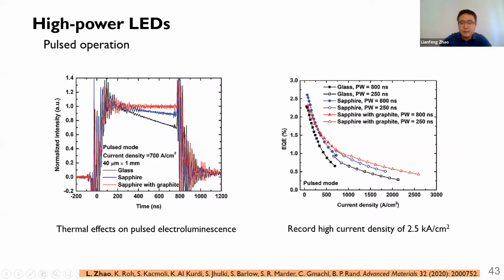We further studied the device during pulsed operation mode. In the pulsed operation, the devices will have more time to cool so that they can be operated to an even higher current density. But even during the pulsed operation mode, thermal management is still important. For example, here, the black curve shows the control sample without any thermal management. And you can see even for a small time period, like 800 nanoseconds, the EL decreased a lot because of the joule heating. But here, after applying the sapphire and the graphite layers, the EL light intensity is very stable. This really shows the importance of thermal management.